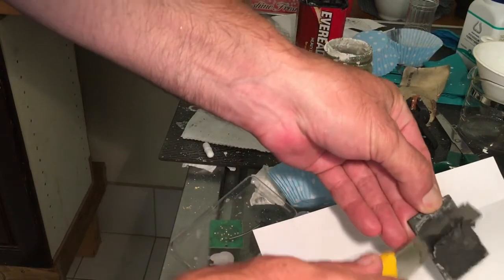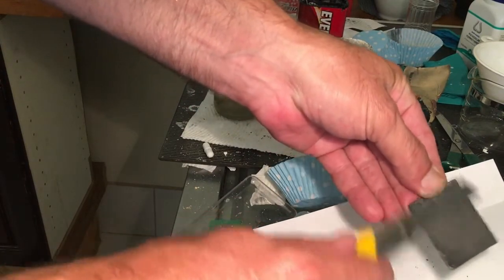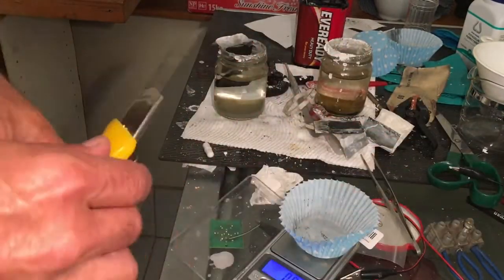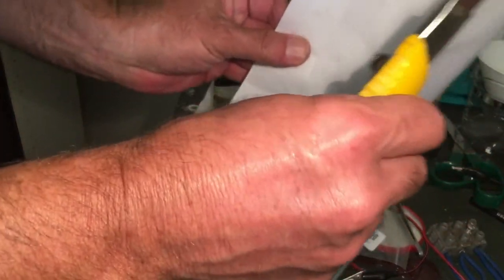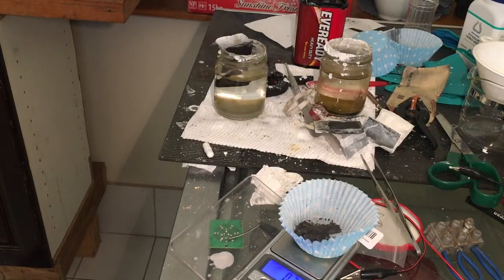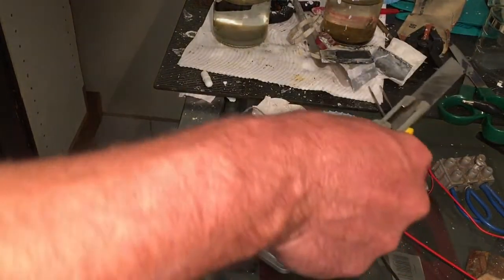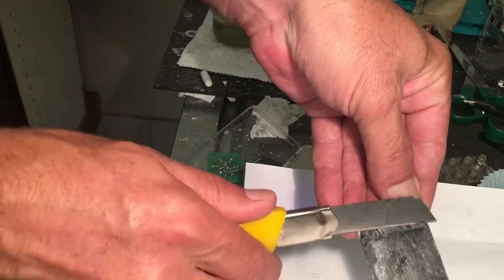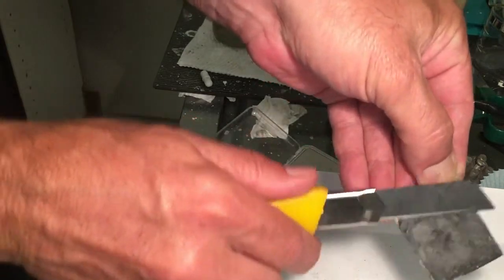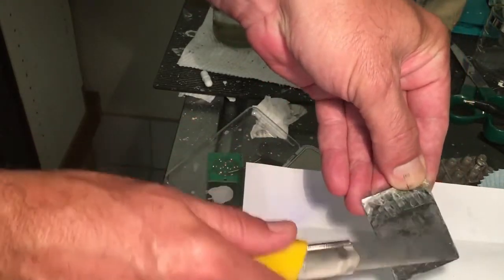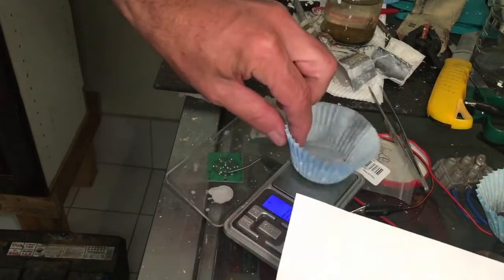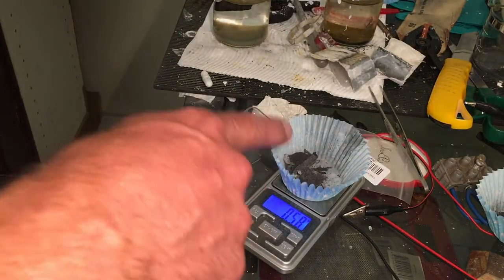So this is the newest cell. So it didn't really bind. That come off quite easy. And for the weight of it plus binder, 0.7 grams of material. So that's that one. And we'll try the other one, the original contaminated material. I think I'll just go back to painting it on paper then trying to coat it. Seems to be a better way to do it. And the contaminated version, 0.5 grams. So that one performed way better with less carbon and stuff on it than the second attempt at the cell.